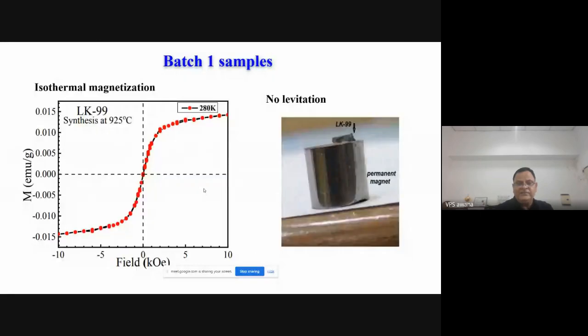Well, after this, we measured this sample for its magnetization, and we found that it is not diamagnetic. In fact, it's paramagnetic. There was no levitation. The sample could very well sit idly over the magnet, and we could see there is no levitation. Of course, we put our findings immediately on 31st of July on arXiv, and we said that for us, as of now, the compound is not superconducting. So we will see whether it happens or not, and we'll try more samples.